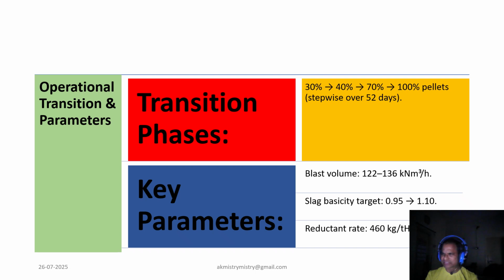So the transition is not very abrupt. When we ramp up, it's quite needed that we go from a small quantum to a higher quantum, as shown in the slide, where pellet use increases from 30 to 100% over more than 40 days. So we have to keep blast volume within a stipulated band, which also ensures the stability of our blast furnace process. Also, it is needed that the target slag basicity lies from 0.95 to 1.1, and it is also achieved with a reductant rate of 460 kg per ton hot metal, as shown.